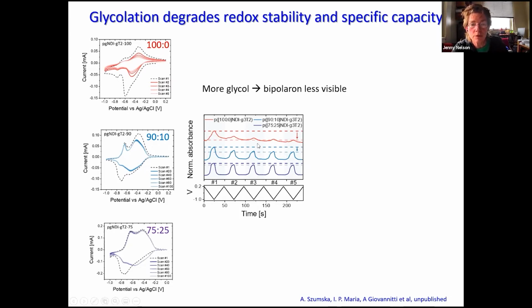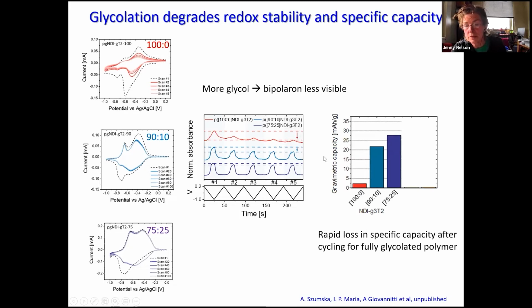And the consequence of this is that if after a number of cycles you measure the specific capacity of the polymers, you find that it's been very much affected by this loss in performance of the glycolated polymer, whereas with the partly alkylated polymers, the loss is much less and the specific capacity is more like what it is in the very first cycle. So this is quite interesting.